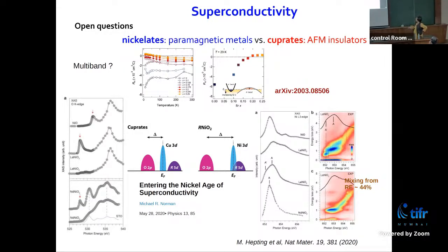Now, this is again some of the oxygen K-edge X-ray absorption spectroscopy, and it shows that this oxygen peak is basically absent. So that means the cuprate is in the charge transfer regime, because I mentioned the all-importance of the oxygen, whereas the nickelate is in the Mott regime, with oxygen not having much role.